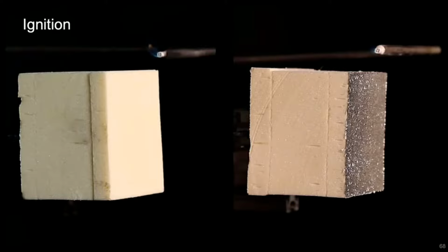We'll see the char will then crack, allowing flammable gases from deeper within the sample to exit the front face, and flaming will then persist for several minutes before again extinguishing. On the right, with the foil facer present, we'll not see any ignition at all for the full duration of the experiment. I'd like to remind you that the foil facer on this product is only about 30 microns thick. That's 30 thousandths of a millimeter thick.